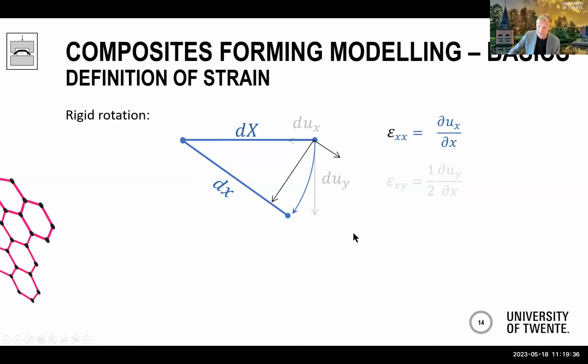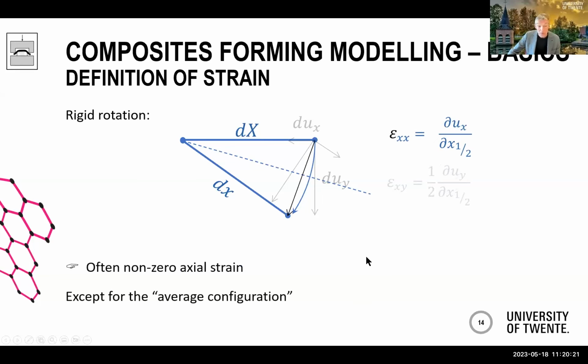If we translate this to a stress, then this rigid rotation generates huge stresses because of the large modulus in the fiber direction. So that's not what we want. And only if we take the intermediate frame of reference halfway, then we can make the displacement in the x direction equal to 0. But then we need the intermediate configuration. Okay, this is nice, and this is well known in large deformation finite elements, the Hughes-Winget algorithm. So that's pretty standard by now. Often we get a non-zero axial strain except for the average configuration. So you should use the average configuration to evaluate your strains and your stresses. Okay, nice.